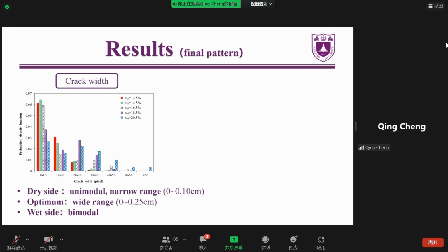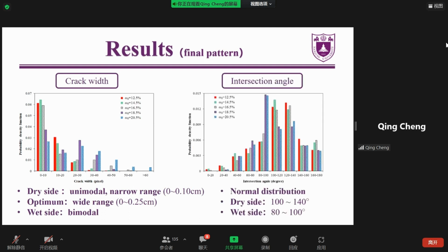And the figure on the left-hand side shows the probability density function of the crack width of each soil sample at the end of the desiccation test. Generally, with increasing compaction water content, we can find that the probability density function of crack width changes from a unimodal form to a bimodal form, indicating that the grading characteristics of the primary cracks and subcracks become more obvious. In terms of the probability density function of the crack intersection angle, it is basically a normal distribution.